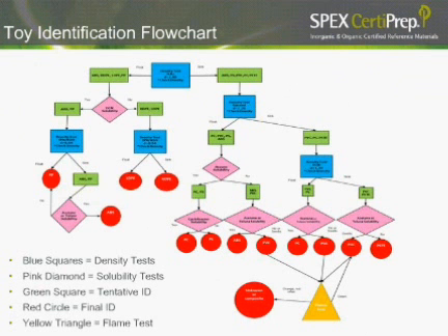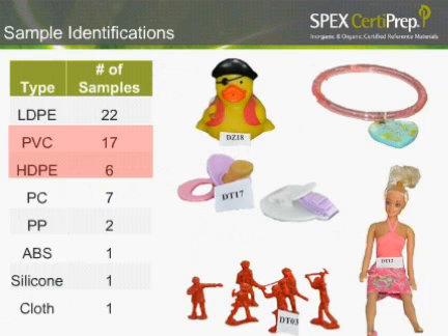What we ended up with was this kind of convoluted flow chart, which allowed us to do different density and solubility tests to give us tentative identifications for our different polymers. In the end, what we found is the highest percentage of polymers in our toys were our polyethylene polymers and our PVC. We did have a couple of polycarbonate samples, as well as an ABS and a polypropylene. We also had a cloth sample, which was the doll's dress, and a silicone sample, which was the nipple of the pacifier. Overall, we decided to focus our analysis on what we were deeming to be some of the dirtier plastics, like the PVC, and some of the cleanest plastics, which we believed were the HDPE.